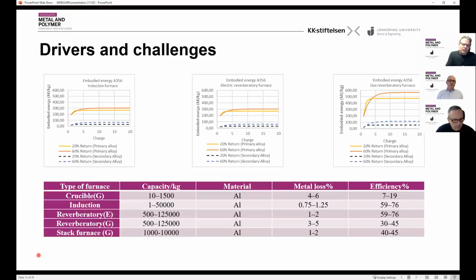And if you look at the electrification of the industry, you can compare the efficiency of a number of furnaces, and all that are electrically driven, they all have lesser material loss during production. So if you have a crucible furnace, you have a relatively high loss. If you use induction, you have lesser loss. The same thing is if you compare a reverberatory furnace to a gas-driven such with an electric furnace. It's a difference. And also the energy efficiency in the furnaces is increasing. So that means that the power requirements are reduced, the material losses are reduced if you use electrical power.